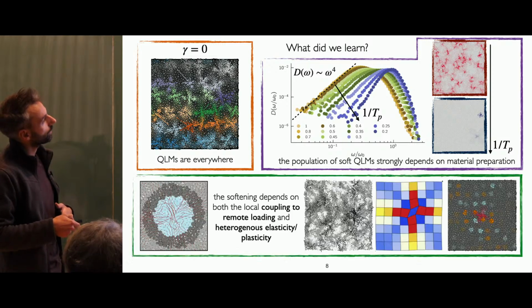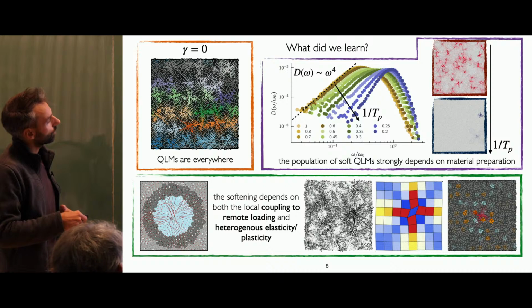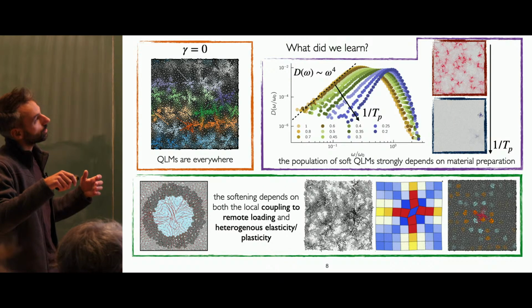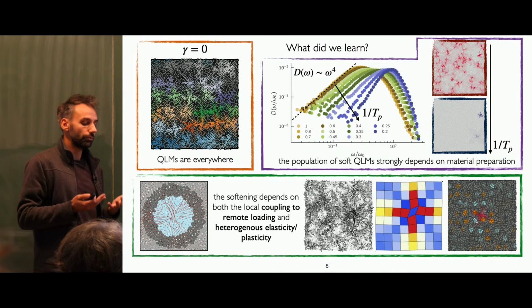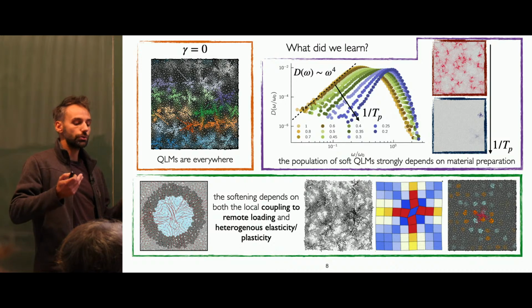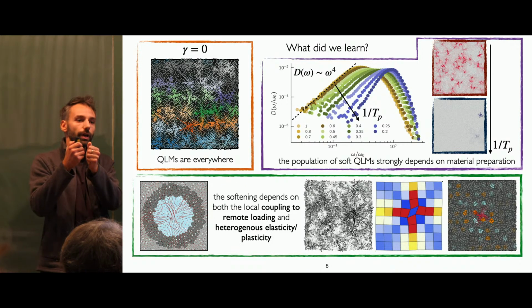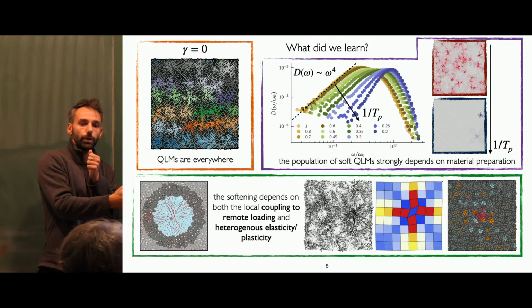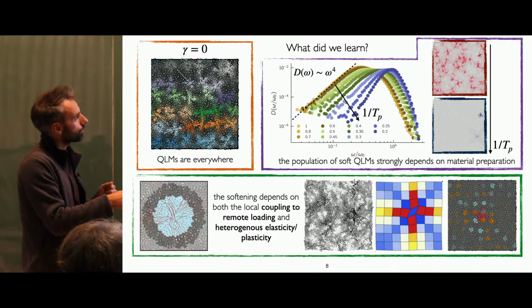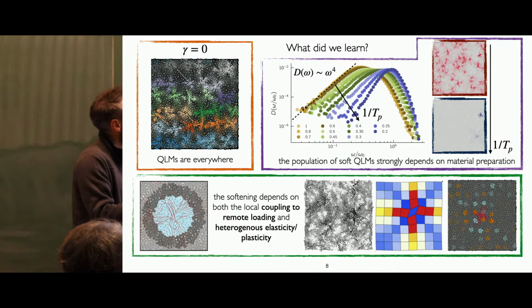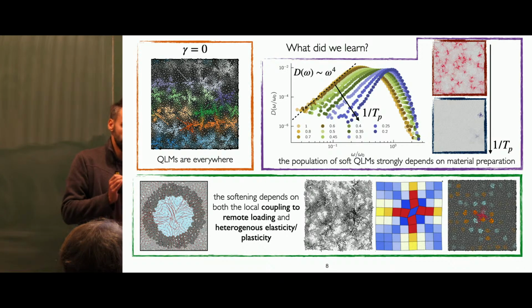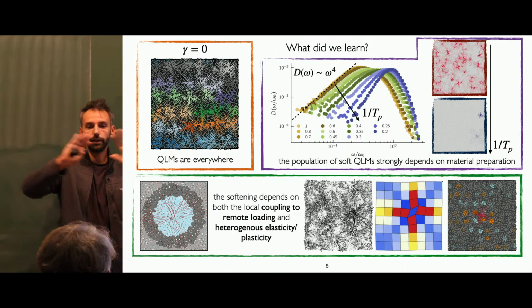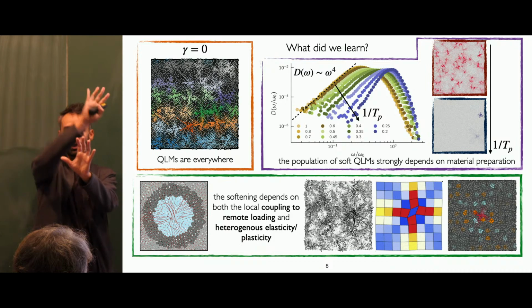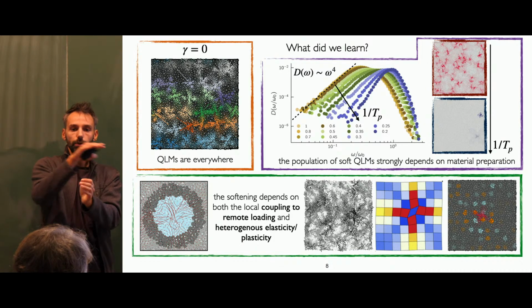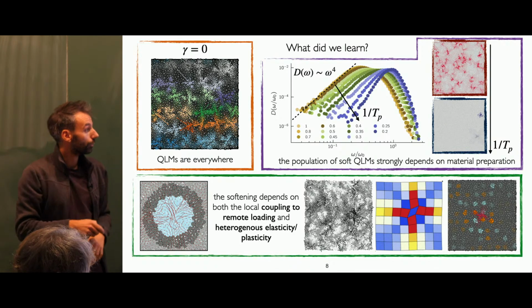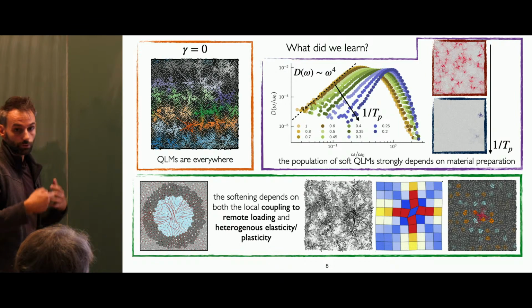And from the point of view of mechanics, we also learned a lot. First of all, if I'm making a map and telling you how soft it is just in terms of the mode frequency, it doesn't tell you anything about mechanics, because what you would like to know is not only the frequency of the mode, but how it is going to soften or stiffen upon deformation. And what we learned is that modes have an internal coupling. So for example, if you use a method like the local yield stress centered around the mode, and you forget everything else, so you're freezing everything and you're just shearing it, so you're not talking to any other part of the system, already at that level, if you change the orientation of the shear deformation, you will see a different coupling. So internally, they have a coupling with the remote loading.